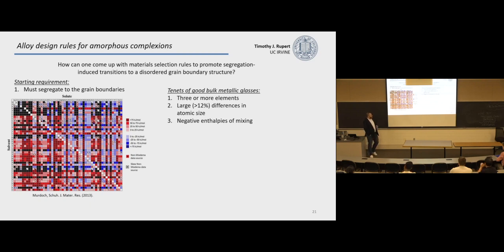The difference in our work is that we basically need to have segregation, but then for that grain boundary region to be a good glass former. All right? Again, people have studied this separately, so you can start to look at what has generally worked. So the rules for what makes a good metallic glass are you usually need 3 or more elements, you need large atomic size differences between the elements you're putting in, and you need negative enthalpies of mixing. So we're going to start poking at this and see if this combined set of rules works well for choosing materials.